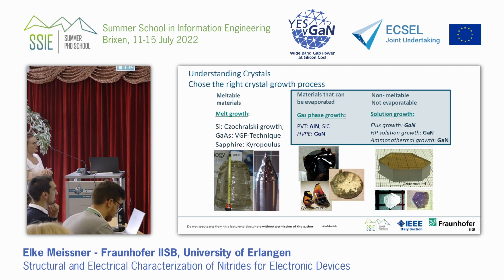So if you have a material that you can melt, it's very easy. There are many examples of this, but this is not the case for the nitrides. The nitrides come into play if we talk about materials that can only be evaporated and not melted. Then you have aluminum nitride, for example, by physical vapor transport, so PVT processes like silicon carbide, and the HVPE process, which is a chemically mediated gas phase process, for gallium nitride. And if you do some solution growth, you can do this if the material is not meltable and if you cannot sensibly evaporate it. This is where high pressure solution growth, the sodium flux method, and ammonothermal growth for gallium nitride come into play.